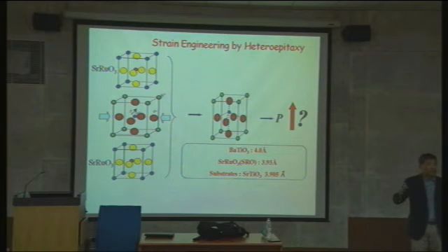So this thin film actually has compressive strain because it accommodates the underlying tile. The tile is smaller, and I want to put a large tile on it, so you have to compress it, and this is even more compressive. So 4.0 angstrom to 3.9 angstrom is a very large lattice mismatch, and this lattice mismatch is too big, so you cannot really grow reasonably thick films without relaxation. This is very similar to the case we have seen with strontium ruthenate on lanthanum aluminate: the large lattice mismatch and relaxation.